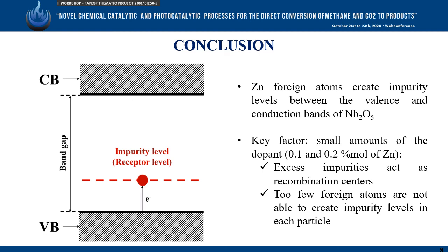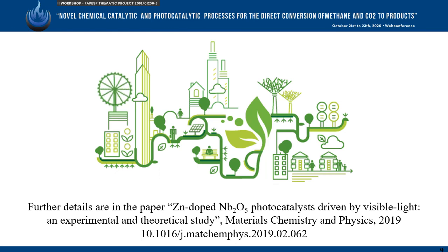However, the key factor responsible for the remarkable improvement of the sample's photoactivity is the use of very small amounts of the dopant, since excess impurities act as recombination centers and too few zinc atoms are not able to create impurity levels in each particle of niobium pentoxide. For further details, please see the paper published in Materials Chemistry and Physics.